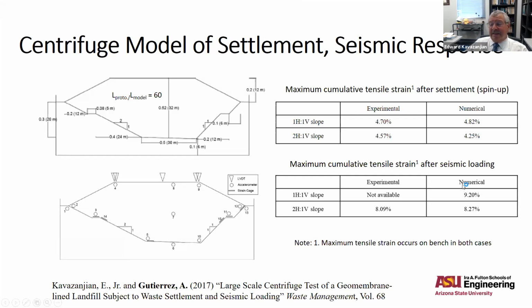And this may not sound like a lot of strain. 4% may not sound like a lot of strain. 9%, it's getting there. The tensile strain of HDPE geomembranes are typically on the order of 11 to 14%, depending on the geomembrane. But as you'll see, there are a lot of factors that we need to consider that make these strain levels perhaps unacceptable for liner performance.